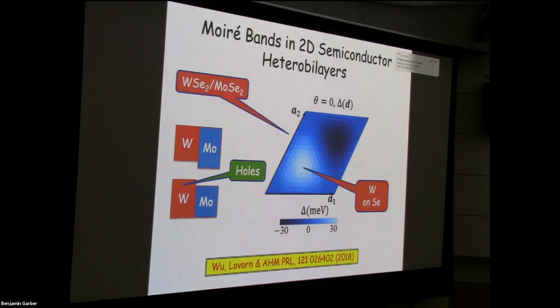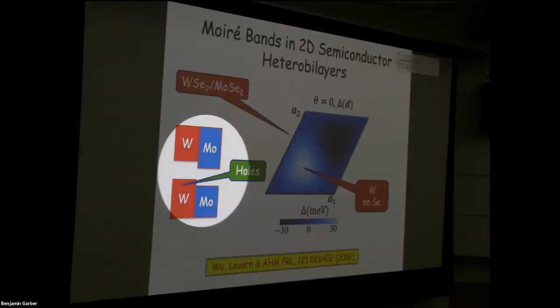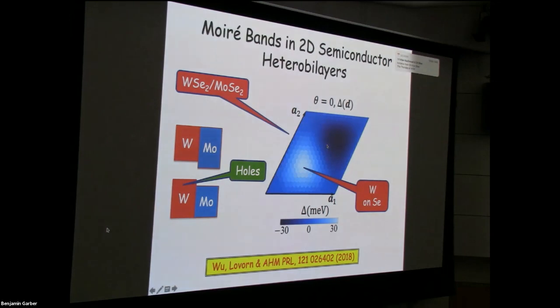If you have a Moiré pattern, then the local stacking arrangement between the two single layer semiconductors is varying slowly in space, and that moves the top of the valence band up and down. So this system is described by a model with a periodic potential that has the periodicity of the Moiré pattern, for some effective mass electrons that have a spin degree of freedom. In other words, this is more or less exactly a Hubbard model.